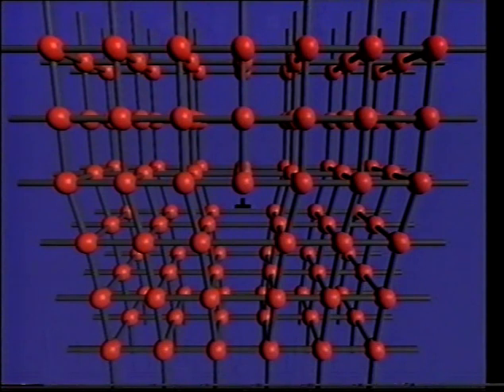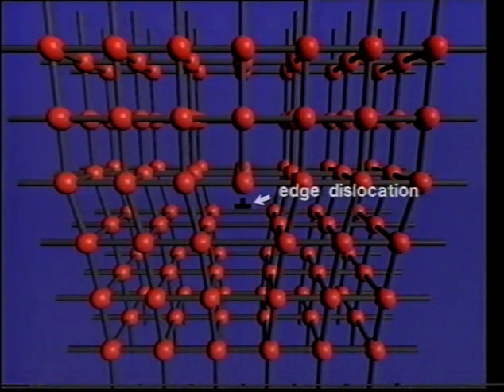Names are helpful here. The edge dislocation is so called because it lies along the edge of a plane of atoms or ions that terminates within the crystal. This diagram shows a cross-section through a crystal where the terminating plane of atoms can be seen edge on. It would be coming out of the crystal towards you in a straight line. This symbol is often used to represent a dislocation.